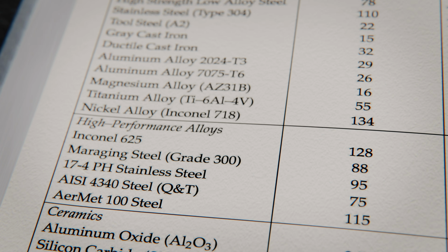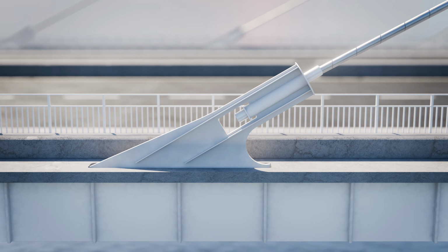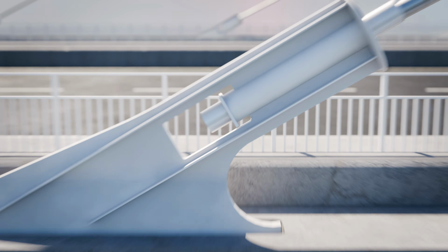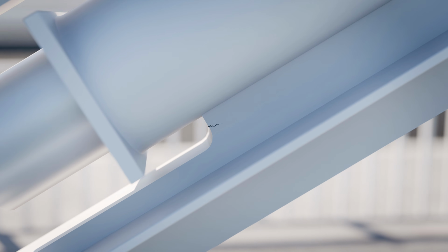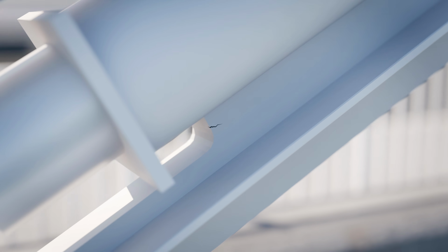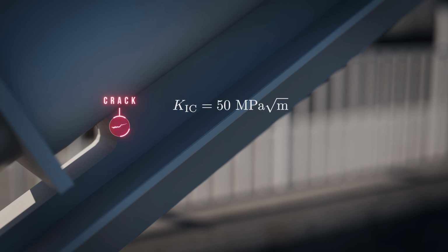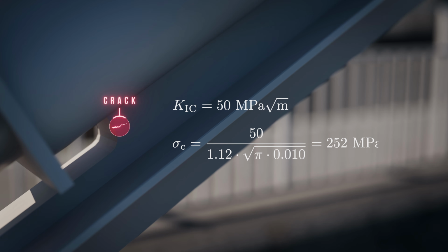Imagine you're the engineer responsible for the structural integrity of a bridge, and during a routine inspection, you discover a crack in one of the stay cable anchorages. You know the fracture toughness of the steel from lab testing performed during material qualification. Using the stress intensity factor equation, you can calculate the critical stress at which the crack would propagate. For a crack length of 10 mm and a geometry factor of 1.12, the critical stress is 252 megapascals.